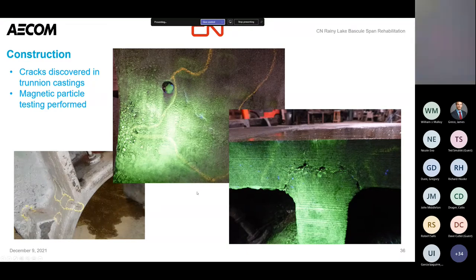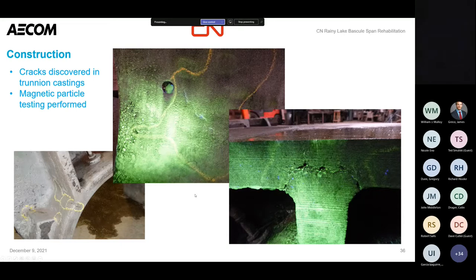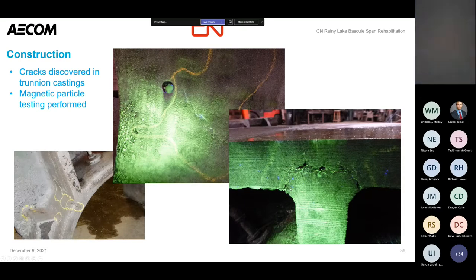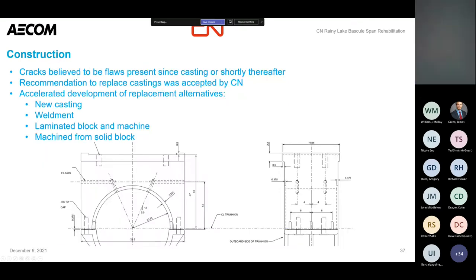Cracks are a bad thing in steel. We read through the report and considered all possible causes. We determined these cracks were likely there from the original casting during cooling, or appeared shortly thereafter — not fatigue cracks. This trunnion sees no stress cycle: the counterweight is always sitting on top of it, and even when the bridge opens and closes, the counterweight load is consistent because the counterweight always stays vertical. So we weren't really concerned about crack growth due to fatigue. But when we find cracks in steel elements, it's not a good thing, so we did recommend to CN to replace the castings, which CN accepted.